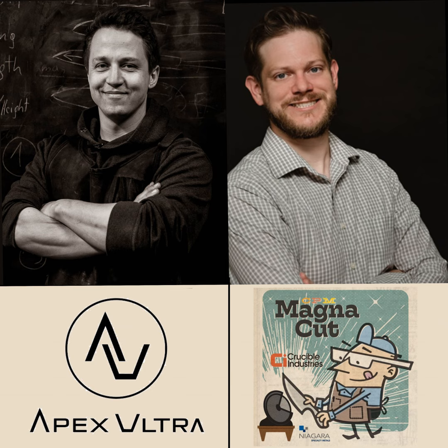We've had stupid things happen to us, like a total power out while our ingot was remolten. So you just lose like 600 kilos and there's nothing you can do about it in the ESR process. Mm-hmm. And is that what happened in the first batch? That happened in the second batch, I believe, or in the second or third batch. It wasn't a total failure because we still had 2/3 of the ingot, but we lost 1/3 of the ingot. And they don't even compensate for that. They just say, here you go, here's the scrap value. You get €1 per kilogram, and we don't charge you for this third of the material that we totally messed up.